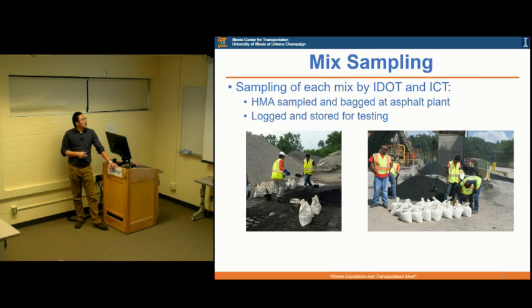So we did a lot of testing. Of course, we're going to get our samples. I think this is Puneet - he helped get a lot of samples at the asphalt plant. We basically get all the loose mix at the asphalt plant, ship it to our lab, do the lab compaction, and then prepare all the mixes in our lab.